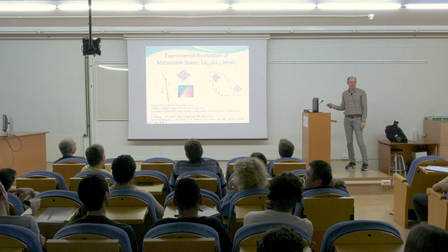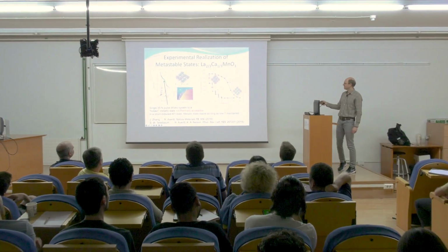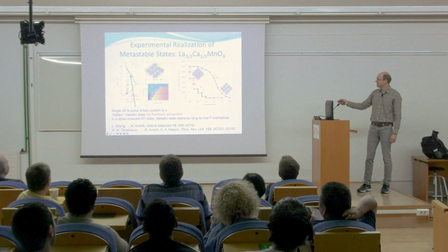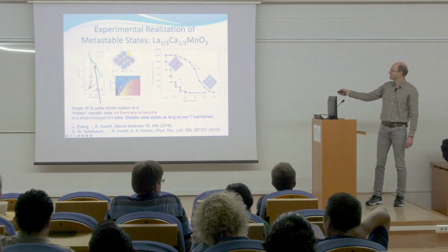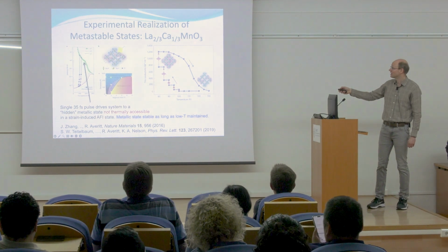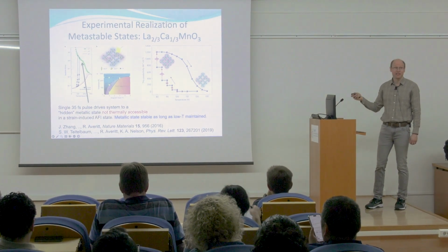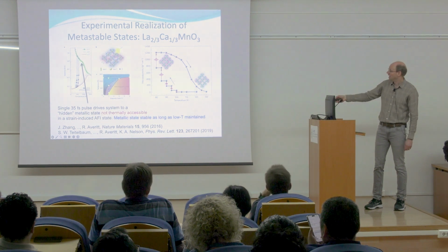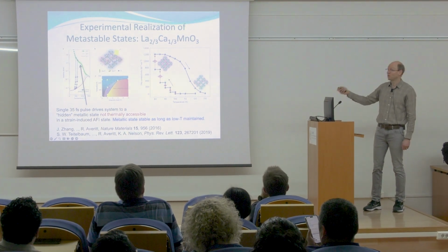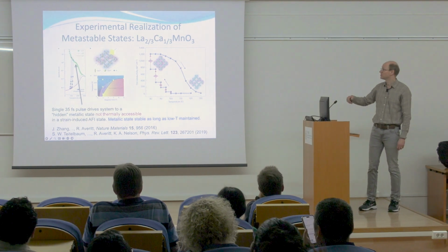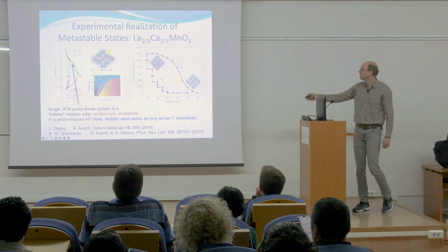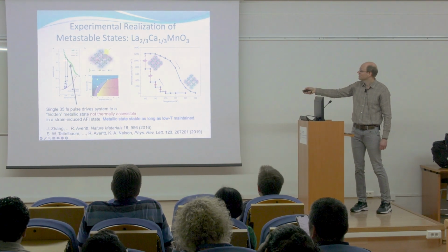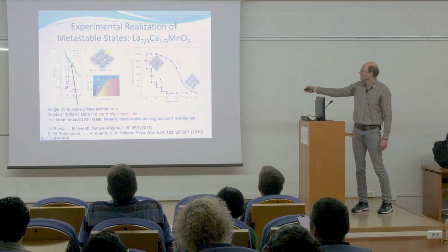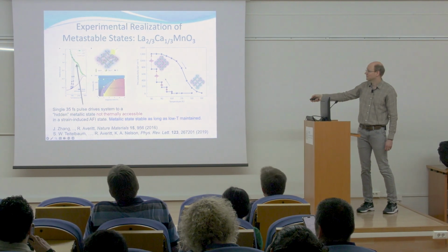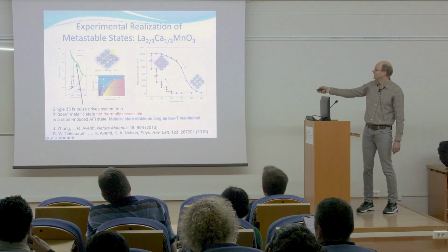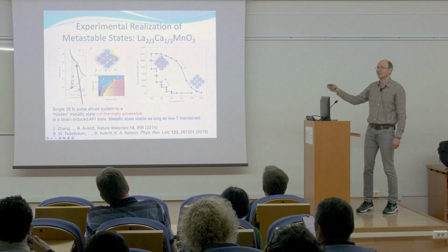All right, so as a second example, which is similar in some of the phenomena, but different in details. This is a very different material. This is lanthanum, calcium, manganese, oxygen. This material is electrically insulating, but it has a magnetic order transition as opposed to a charge order transition in the earlier example. So the green curve in this case is what you get as you lower the temperature, and you hit it with a 35 femtosecond pulse of light, just like before, and then the resistance abruptly drops to a very conducting regime.